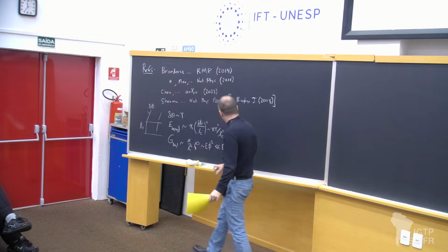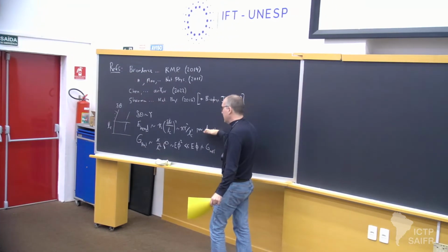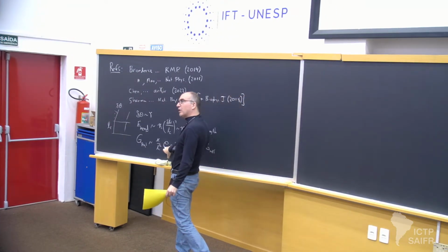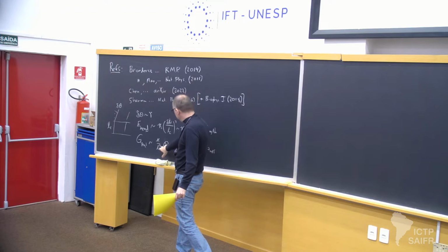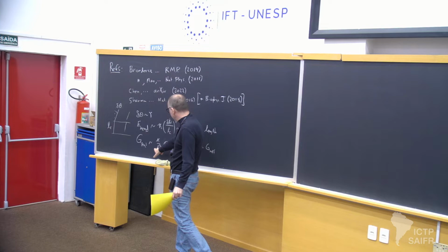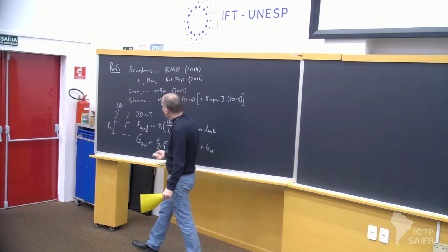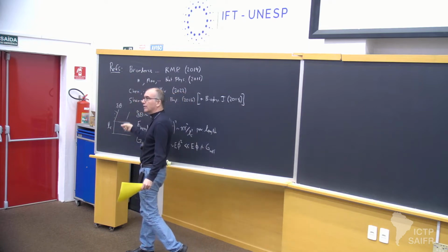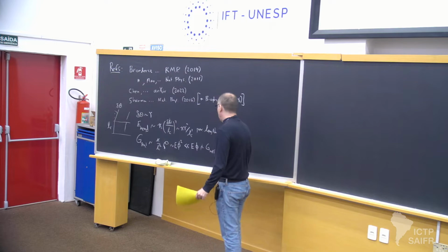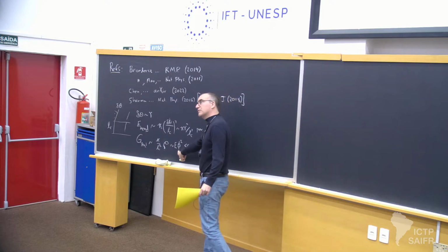That's this term. But this is an energy per unit length now, so I multiply by the length per volume. And since this is proportional to concentration, and as I argued before, if you think of it as a lattice, 1 over the square of the lattice spacing is also a measure of the concentration of this network. That naturally gives you 2 factors of concentration.